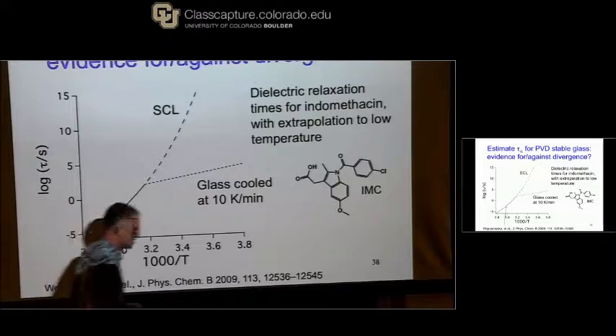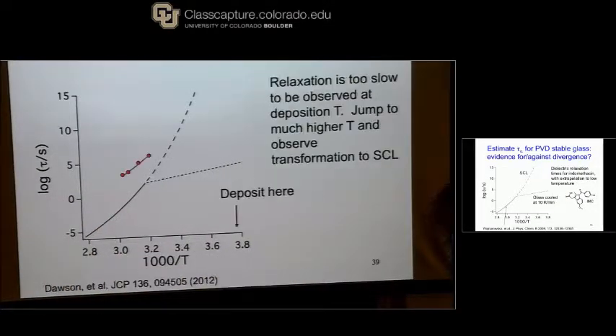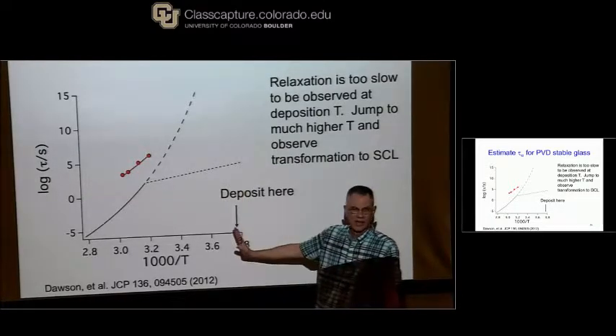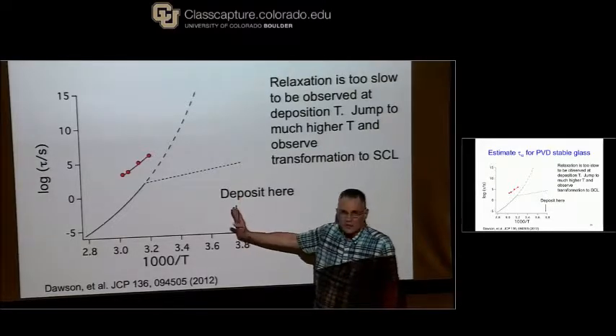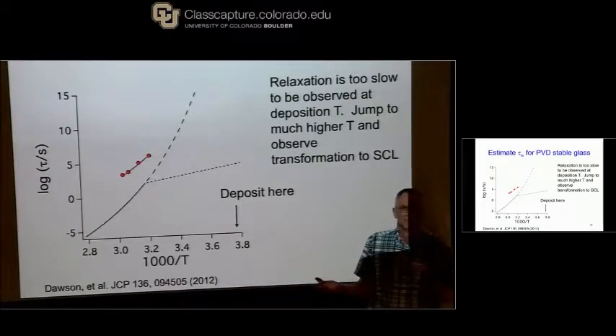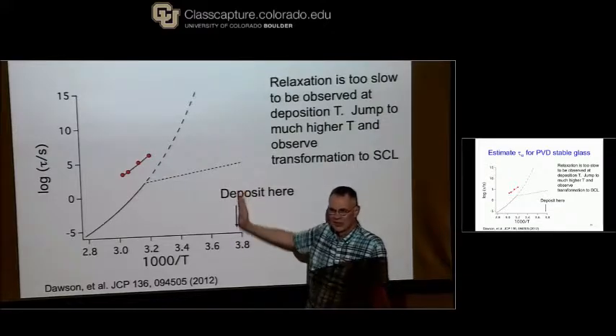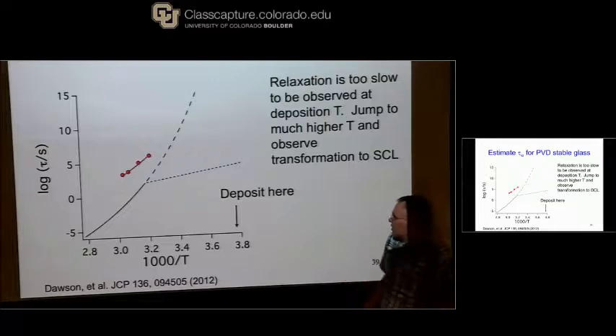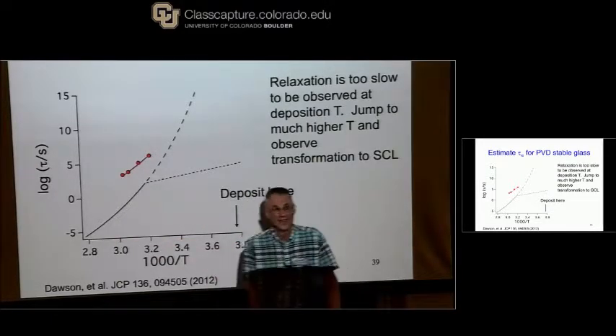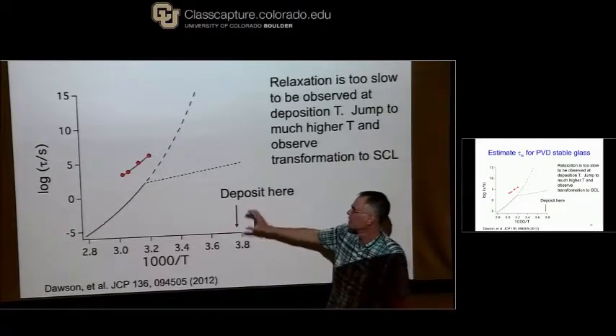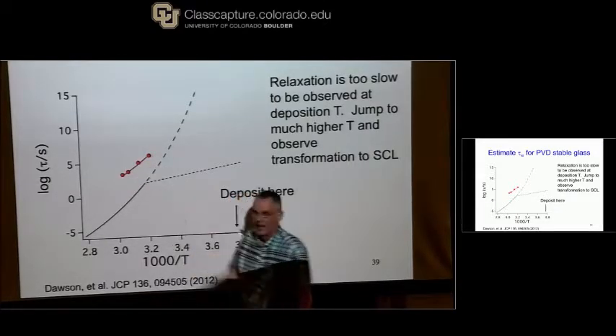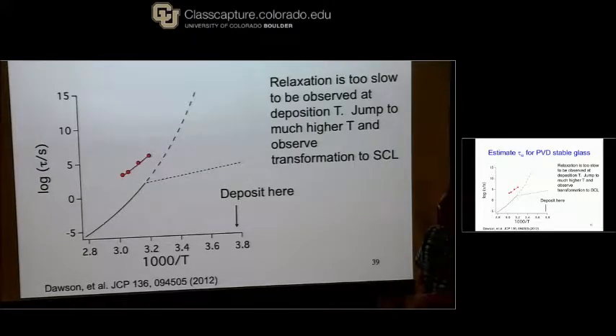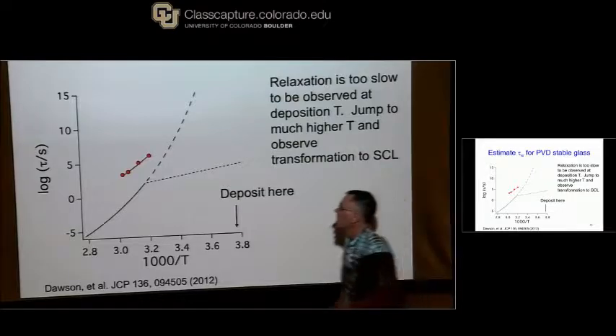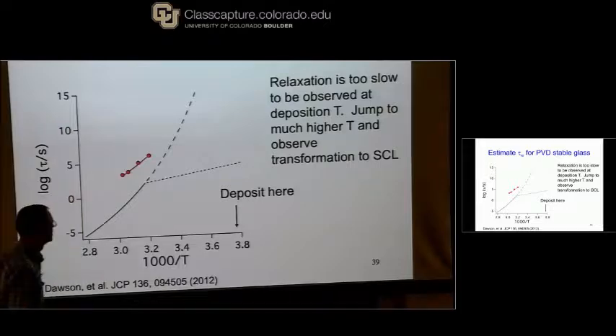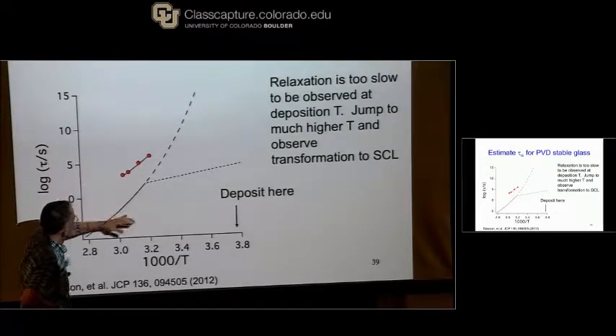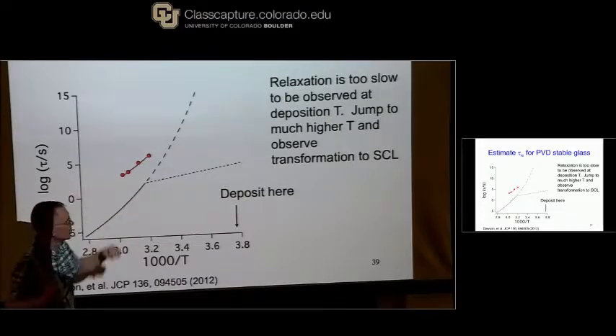Okay, so this is the context. And now where do our vapor deposited materials lie? Okay, so we deposit down here because this is where we make the most stable material. So we've waited around for parts of a day, nothing happens. So I can't tell you really anything about how big the barriers are at this temperature. So you do what experimentalists would do. They say, well, let's heat the sample up and make it fall apart. Okay, so we take a sample, we try and make the same glass over and over again, and then we heat it up to different temperatures, and we measure how long it takes that glass to fall apart into the supercooled liquid. And so those red points, those are honest measurements, okay? And they're from 10 to the 3 to 10 to the 6 seconds. And you can see that those are pretty big times compared to the alpha relaxation time.